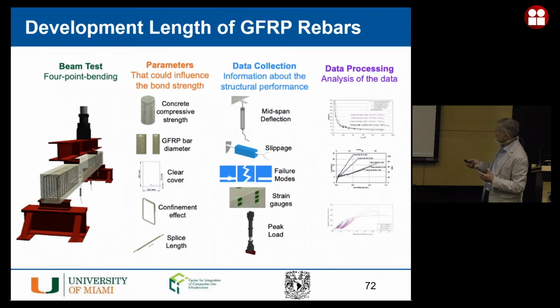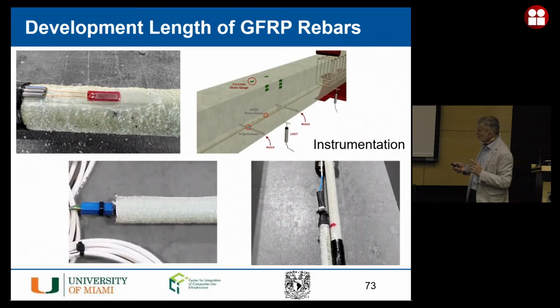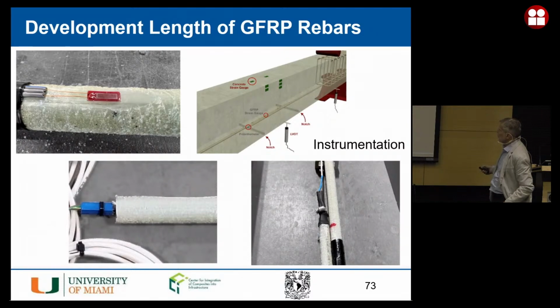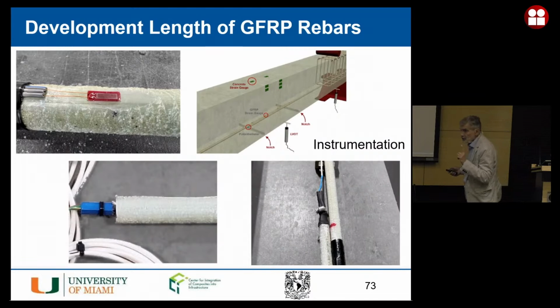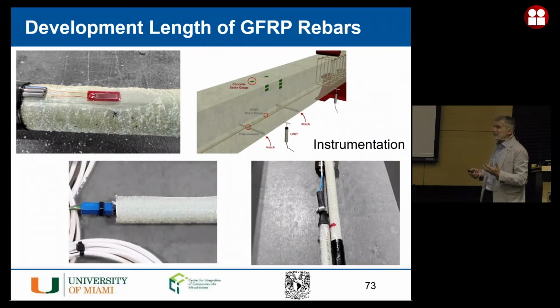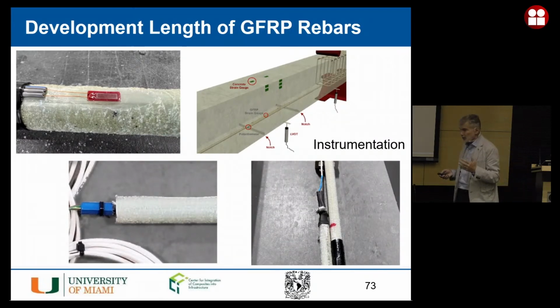So anyhow, that's what we do, and then the data that we collect are indicated here, and then we process them. I just want to show you the best thing that we're doing, which I think is unique because many have done this type of test, is we stick this tiny little potentiometer at the end of the rebar when we are splicing the bars, so we can measure the slip. And then you can see here how the potentiometer is protected, so you can pour the concrete. And the beauty of this, not only you measure the slip, but you do not affect the bond of the bar, because when you apply a strain gauge, you have to clean the surface and make it flat. So you kind of decrease the amount of surface that is really there for bond. So these data are becoming very useful because we measure slip.